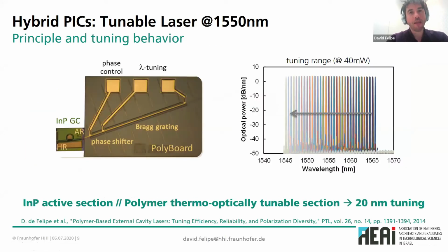Another key element in our technology platform is the so-called hybrid DBR tunable laser. Basically, the structure, as you can see here, comprises an indium phosphide active section that is end-fire coupled to a polymer chip. This section here is a polymer chip on which we can implement thermo-optically tunable phase shifters and Bragg gratings. Thermo-optically, meaning that by means of these microheaters we can change the temperature of the waveguide locally, so heat it. And by means of the change in the temperature, the refractive index of the waveguide changes. With that, we can achieve tuning of the lasing wavelengths, as can be seen here, over a range of more than 20 nanometers.